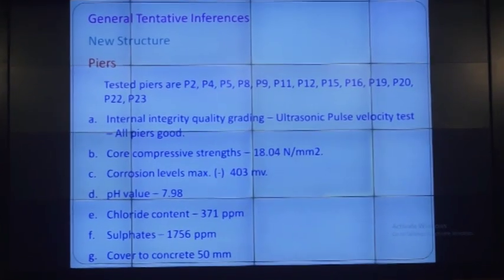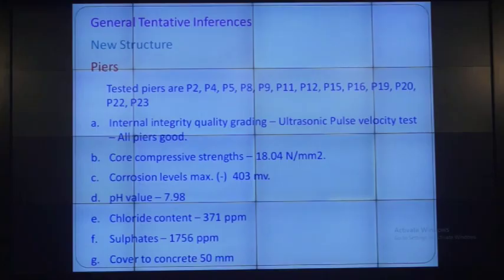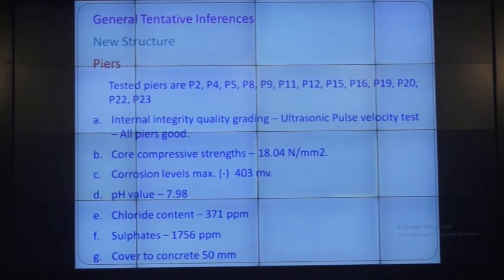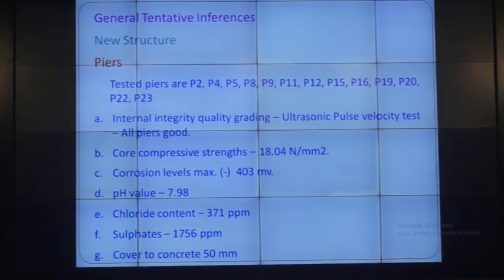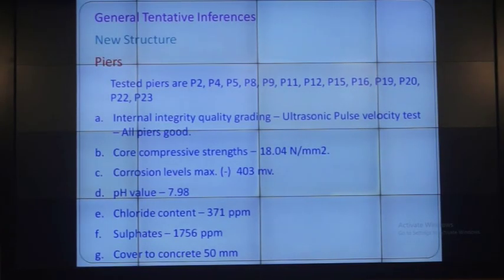Then the new structure, piers, again piers, the circular piers what you have seen there in the first photograph. Piers, again almost similar results are there, 18, corrosion levels are very high, 400. pH is again low, only 7.98.